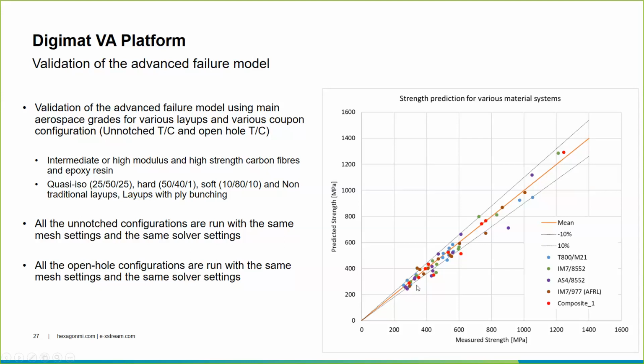So now for each material, each configuration, I just need to position the measured strength. And then you see that what we can easily see is that almost all the dots are located in the envelope plus and minus 10%, with some dots that are exactly located on the orange line. So we can identify that those points are the unnotched tension, and here those are the open hole in compression. So we still have some dots that are outside the plus minus 10%. Those ones typically here and here. Those are mainly for the AS4/8552 materials, and it's also mainly for the unnotched test in compression. So we have probably identified a shortage in the model, and we are working on the possibility to improve the prediction for the unnotched compression test.